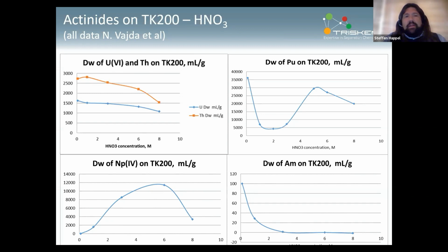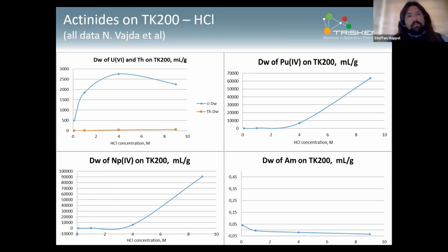So you see, basically, a number of actinides can be retained at pH 2 and then still retained at quite high nitric acid concentrations besides americium. In HCl, it reminds a little bit of one of the UTEVA resin, so quite high retention still of uranium. Thorium pretty much not retained at all. Plutonium easily eluted in dilute HCl, but very strongly retained in high HCl. Neptunium behaving fairly similar to plutonium. Americium not retained at all.